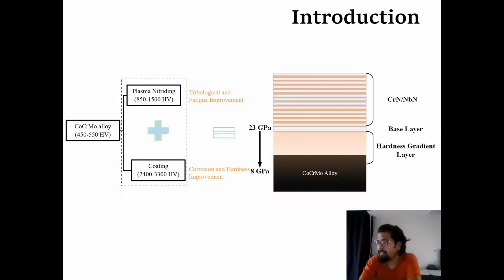So functional coatings are another option, which can increase the hardness from 1500 HV to almost 3300 HV. And so after these two systems, it forms a hardness gradient or stress gradient, which makes this alloy more suitable for the application than originally without any coatings.